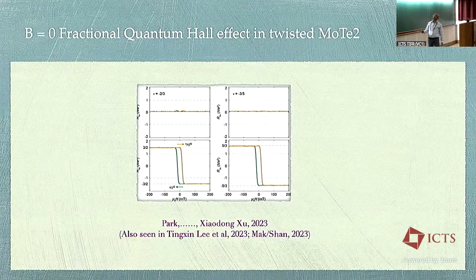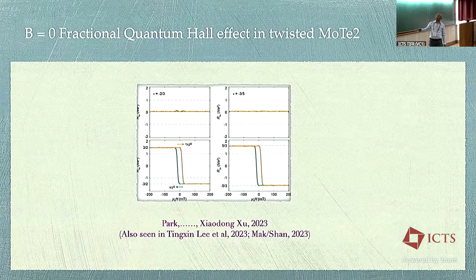This is in MoTe2, and this data is from Xiaodong Xu's group. So this is at a lattice filling of 2/3. There is no magnetic field here, so we're not talking about Landau level filling. We just have 2/3 electrons per unit cell on average, right? And at that filling, as a function of field, if you measure either the Rxx or Rxy, you see this. There is hysteresis as a function of field, telling you that there's broken time reversal symmetry. But beyond the coercive field, the Rxy gets quantized to be 3/2 h/e squared, which corresponds to a fractional Hall conductivity of 2/3 e squared over h. And likewise, this data are 3/5 and so on and so forth.